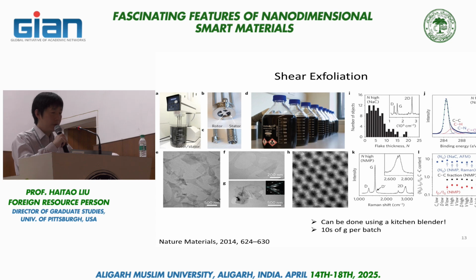And they were able to make graphene pieces using this approach on the tens of gram scale per batch. Imagine you can just go to a kitchen, get your blender, add the water, surfactant, and graphite powder, and you can make graphene out of this very simple setup.